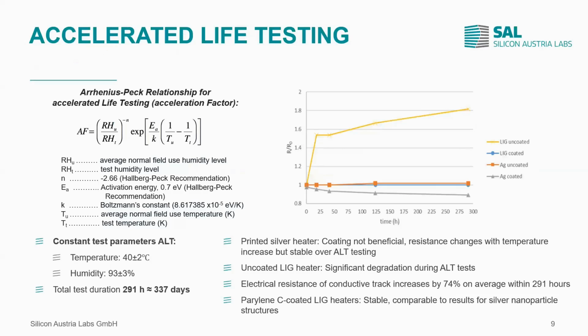So in the next step, we put both heaters under accelerated life testing at 93% relative humidity and 40 degrees Celsius in a climate chamber for 291 hours, which corresponds to 337 days according to the Arrhenius-Peck relationship for ALT. What we have seen here is that the silver heaters, the coated ones and the uncoated ones, and also the LIG heater, but in this case only the coated one, stayed more or less stable over the whole testing time. The uncoated LIG heater started to degrade after not even 1 day, and its resistance increased by 74% on average.